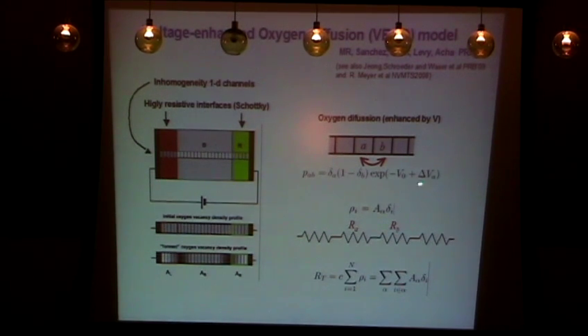Now another important point is that each domain is defined solely by the concentration of oxygen vacancies. Given a certain concentration of oxygen vacancies, delta i, times some model parameter, you get the local resistivity. So the resistivity at each domain only depends on the density of oxygen vacancies. Now the parameter A characterizes whether you are in the bulk or in the interfaces.